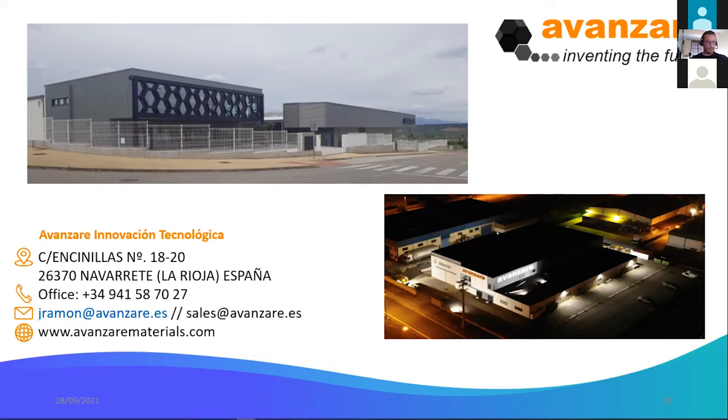I don't know which additive they comment on, but in which step do we add this additive for processing? He's asking, for example, if we need to add it at the beginning, or with the sulfur, with the accelerator, with the filler, in which part? For example, the powder antistatics, you can add with the silica step. The rest of the additives you can add with the processing products. It's not a problem. Usually, with this kind of additives, the processability is quite good.